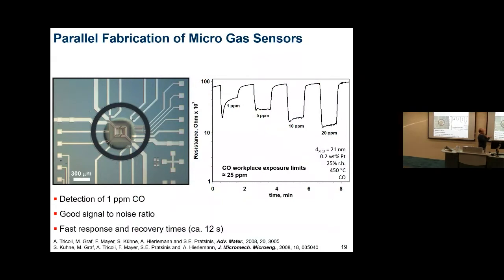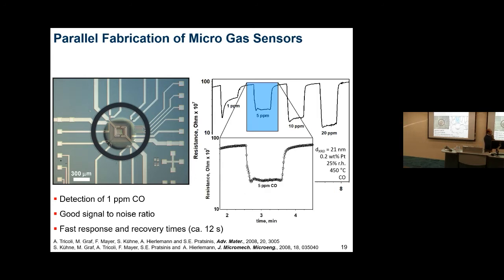This is an example. We just measured the resistance of this metal oxide layer. We have two heaters here and a temperature controller that tells us what the temperature is and keeps it there. And you can measure very rapidly down to 1 ppm or less concentration of CO. If you look at it, this works quite well, with very small response and recovery times.